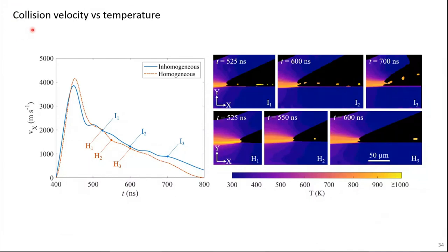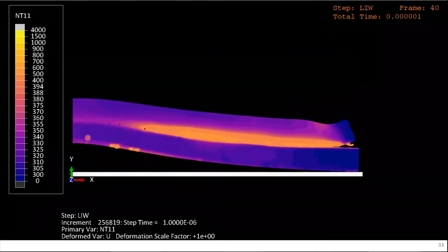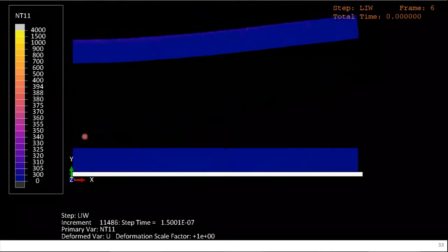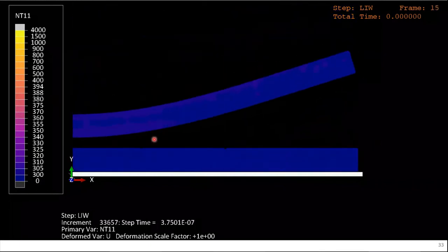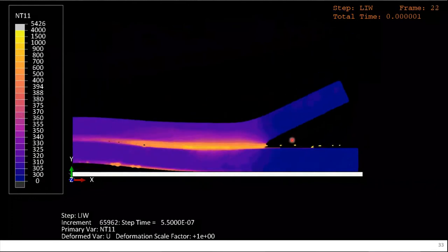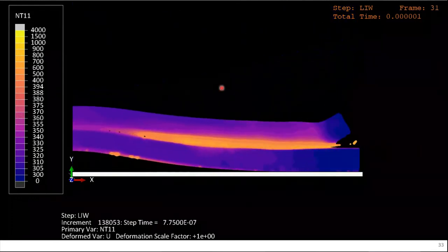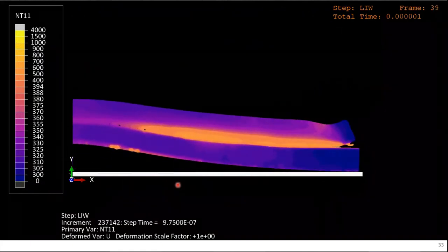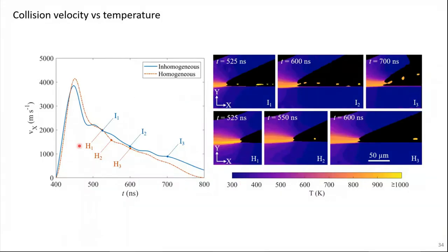Now, if we look at the effects of collision velocity versus temperature, the inhomogeneous is in blue. That means we have microstructure when we consider microstructure. And the homogeneous, when we neglect the effects of microstructure, is in orange. The first thing you notice when you look at this collision velocity is basically, if I track a point where this is connecting, and I track that point as the mouth of this wave closes up, from left to right, that's what you call collision velocity. So the velocity in the x direction for this particular schematic. So if we track collision velocity, which is vx, we notice different profiles.